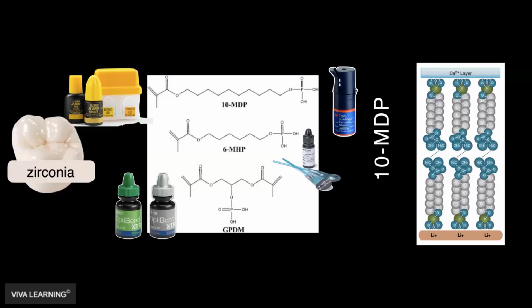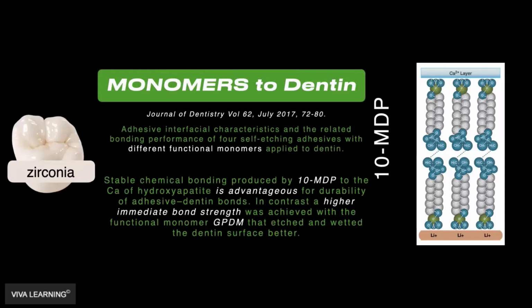Now, Kerr and their adhesive systems, they have 2 chains on the end. So it's a little bit different in the GPDM monomer. Obviously, GPDM has been shown to be extremely successful in enamel and dentin bonding over the years. But 10-MDP is really the one that stands above the rest for zirconia bonding. Now, the reason why Z Prime is such the gold standard in priming is because Z Prime is only MDP. Whereas some of these other ceramic primers have other things in them, Z Prime is just solely MDP. Like it's literally just that.